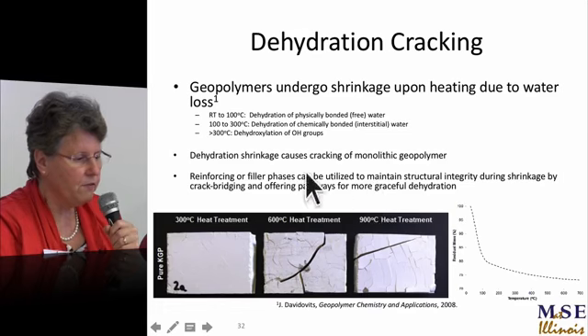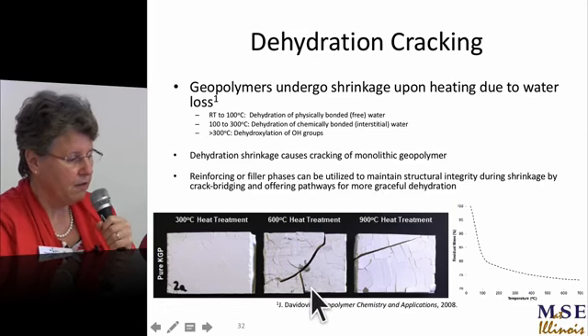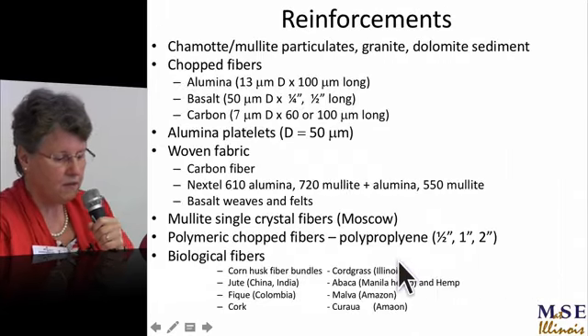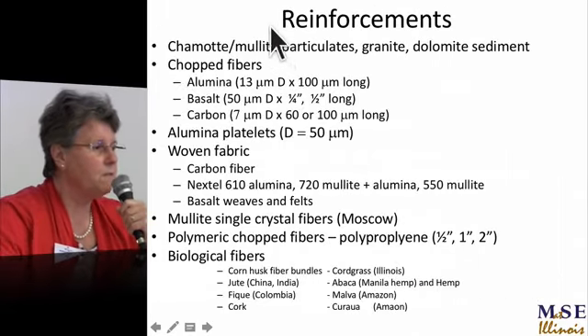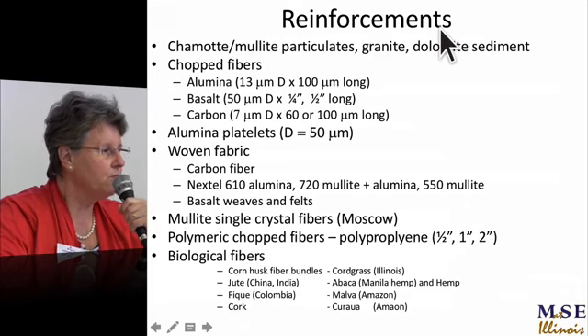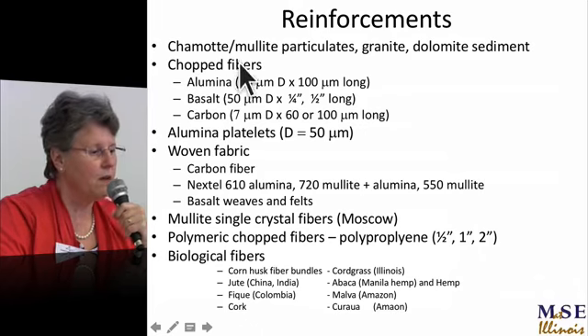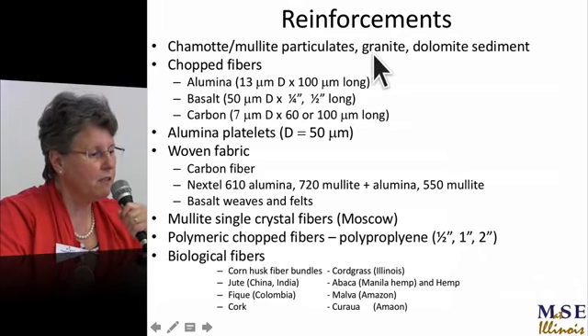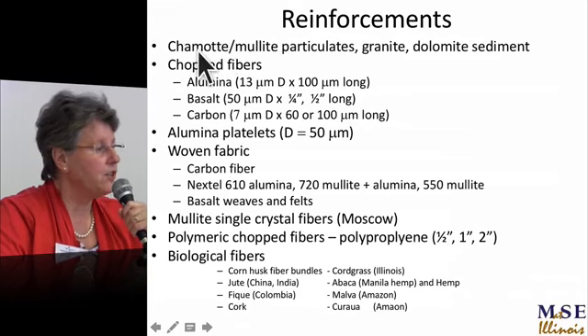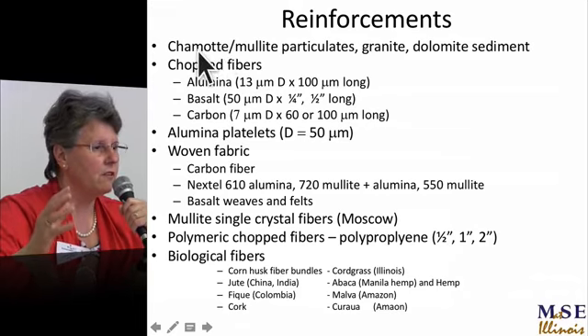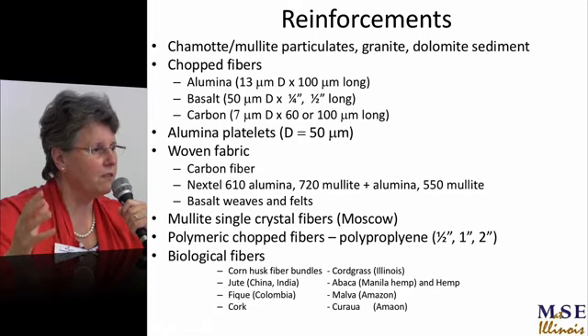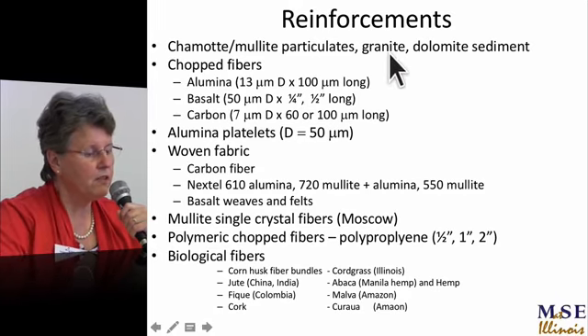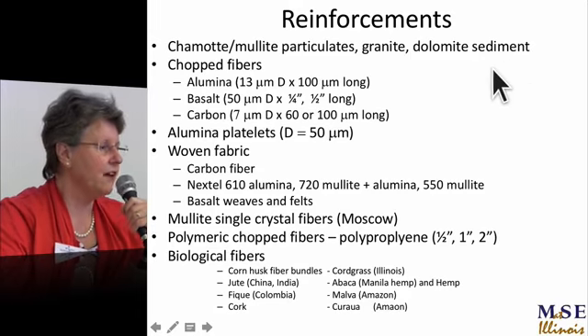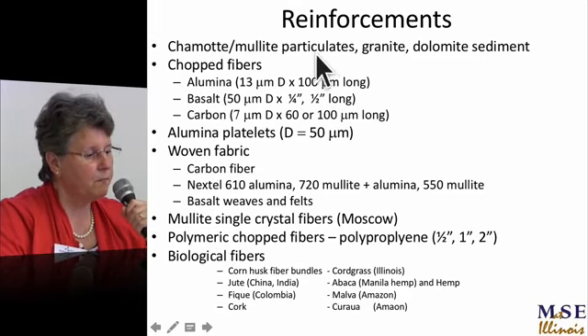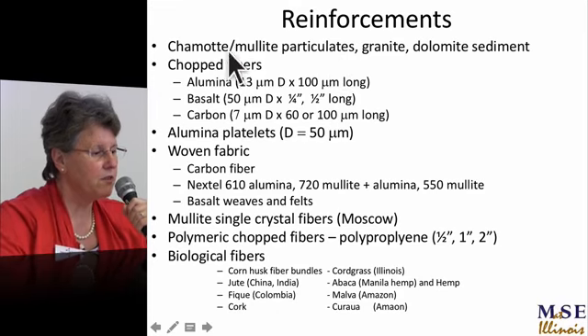Okay, so this dehydration could crack it, and therefore we embarked on a whole bunch of adding reinforcements and seeing what sort of microstructure and what sort of mechanical properties you get. So you can add particulate reinforcements like chamotte, which is calcined clay to produce mullite particles plus silica. That's the mullite particulates, granite, dolomite, sand, whatever. Those are particulates, like zero-dimensional defects.